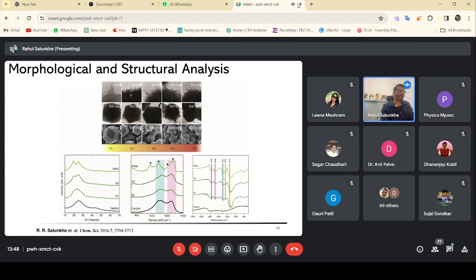So these are the various time differences. We have prepared the samples for 1 hour, 2 hour, 3 hour, 4 hour, and 5 hour aniline coating. And we have taken TEM images, and we observed that the nanorod length goes on increasing, and the density goes on increasing as we increase the time. So we can see a very uniform coating in the case of the 3 hour sample, and after 3 hours the material gets stacked on the surface of the material. It is coating the surface, and that's how it is blocking the inside material, and because of that some problems occur in the 4 hour and 5 hour samples.